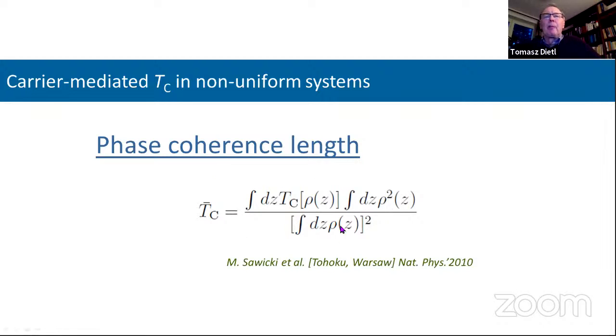Well, if you think a while, you can imagine how to get this formula, but the important physics behind it, which you should always remember in the case of an inhomogeneous system, is that it's not maximum TC, not minimum TC, but some kind of collective state. It's a kind of collective average. Quantum mechanics, as you know, is non-local, and TC is determined collectively by this kind of averaging procedure, which takes into account this non-locality of quantum mechanics.